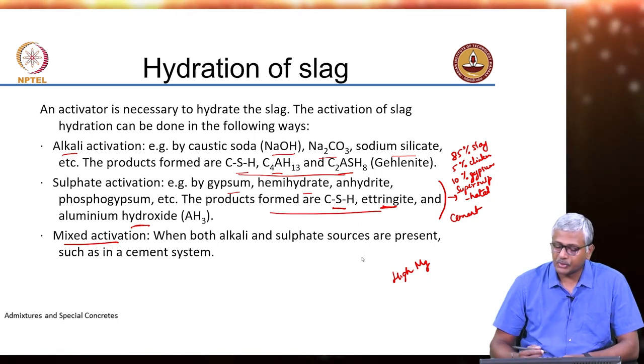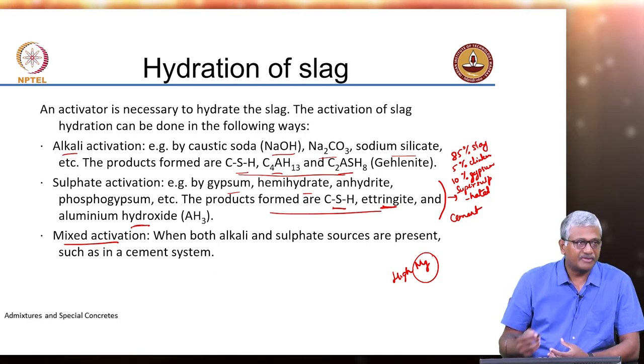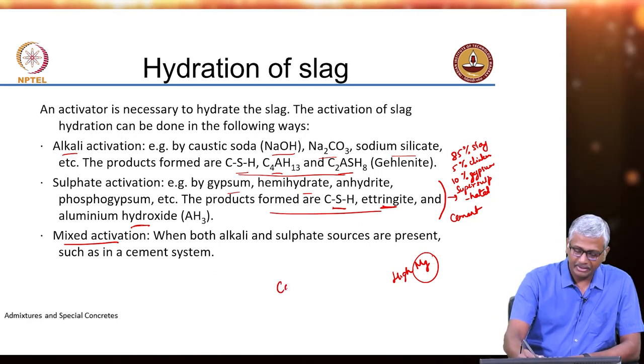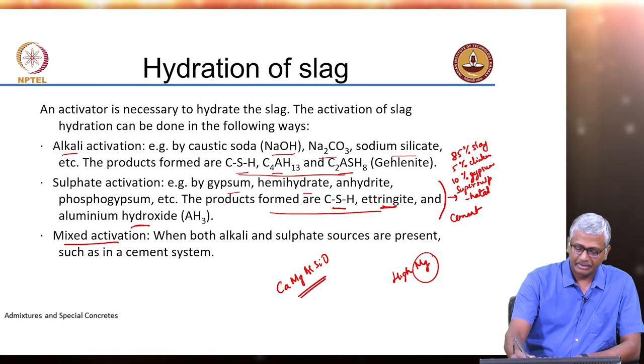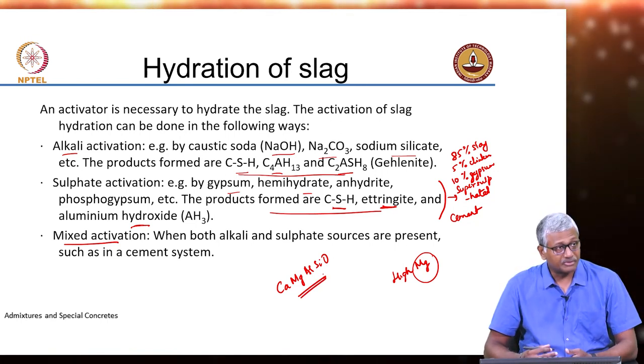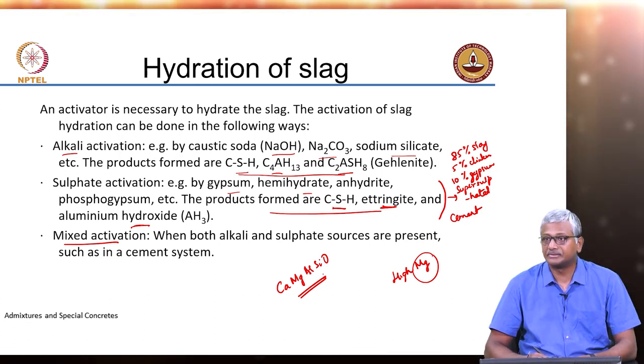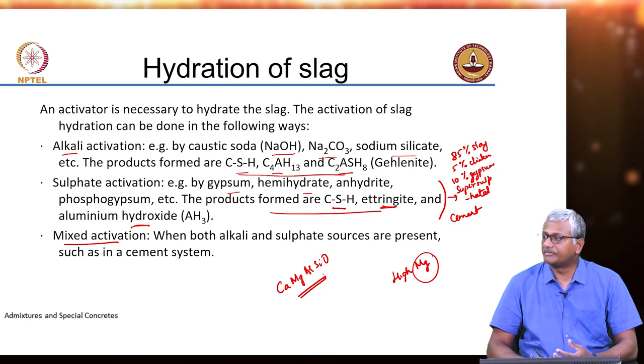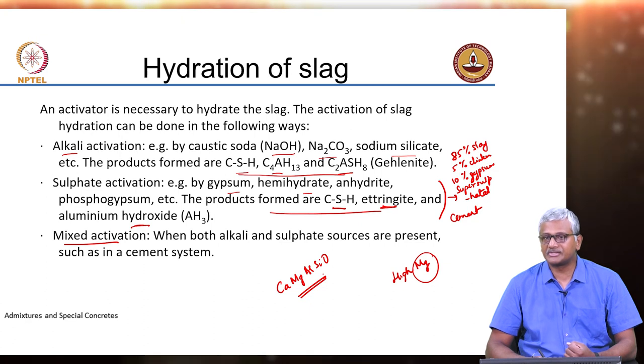Slag also has a high magnesium content. So generally a number of phases in slag are basically calcium, magnesium, aluminium, silicates — complex phases which have all these elements present: calcium, aluminium, magnesium, silica. The difficulty with these phases is that because of magnesium, the solubility of these phases becomes very limited.